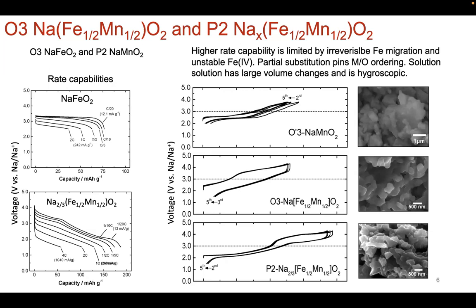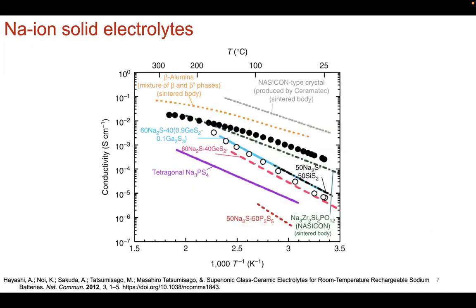So what's happening is there are phase transformations happening with the starting O3 structure or the starting P2 structure. What that means is if there's going to be phase transformation, then we have to deal with electrode material volume expansion and contraction, which usually results in deleterious phenomena like delamination and electrical conductivity decrease. So the electrode that you fabricated is now not as robust as what you started off with, right? It's not touching the current collector as much. Your material is going to start fracturing. You're going to have a host of issues if you don't tighten up the voltage window and also limit the phase transformation. So already there's some engineering that we have to do with sodium-ion cathodes.